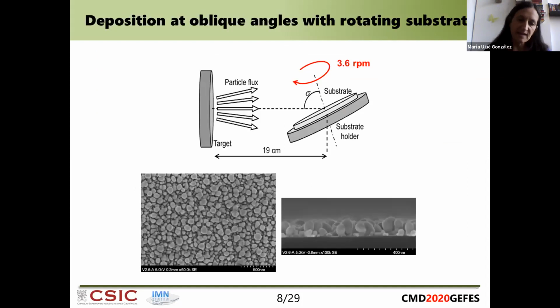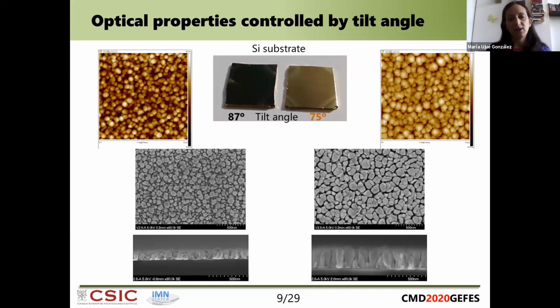In this way, what happens is that we are growing tilted nanocolumns, but as we are changing the orientation continuously because we rotate the substrate, what we are getting at the end are vertical columns, like the ones shown here. So what we realized while doing this is that depending on the tilt angle, the deposition angle, we could obtain very dark gold coatings.